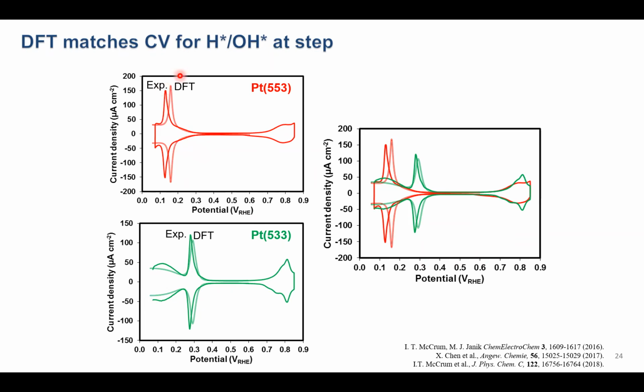But now we can see, if we consider this exchange between adsorbed hydrogen and adsorbed hydroxide and water on the step, we can capture much more accurately the location of these step-associated peaks. We're not shifted way more positive of what's seen experimentally. We match them very nicely. And so now we can explain the difference between the adsorption we saw in the ultra-high vacuum and in the electrochemical environment: in UHV, we can adsorb hydrogen on its own, and in water, we have this exchange on the steps between adsorbed hydrogen and co-adsorbed OH in water.